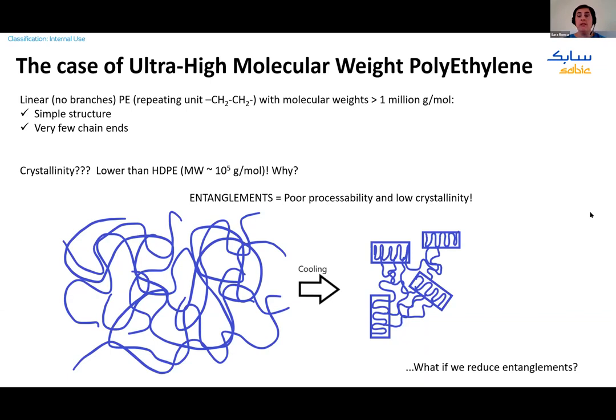The reality is not that easy, because the crystallinity of ultra-high molecular weight polyethylene is actually lower than that of its lower molecular weight analog, high-density polyethylene. The reason for this is chain entanglements. Being a thermoplastic, it needs to be processed in the melt, and when you go into the melt, all these very long chains tend to entangle so deeply that the movement of the chains is very difficult. You get a very high melt viscosity that hampers the formation of crystalline portions and also hampers the processing of the material.